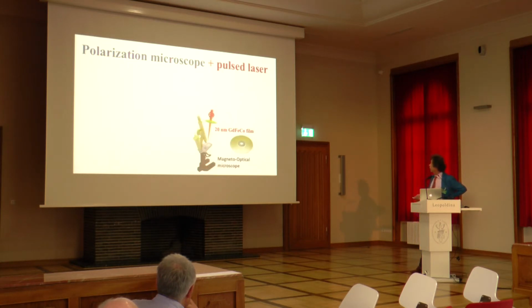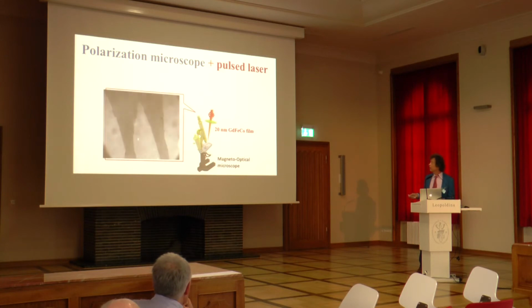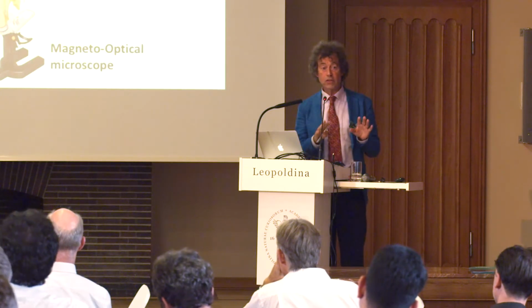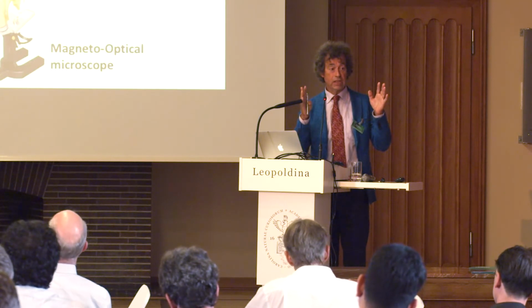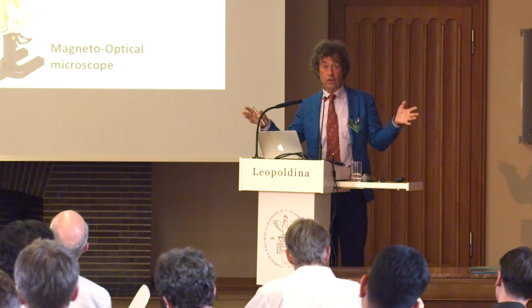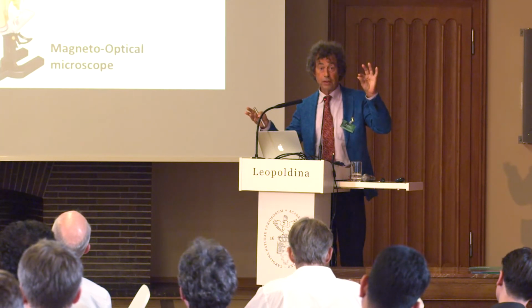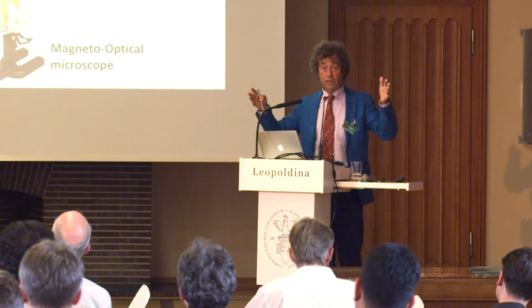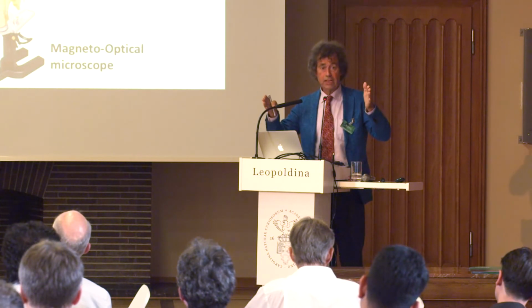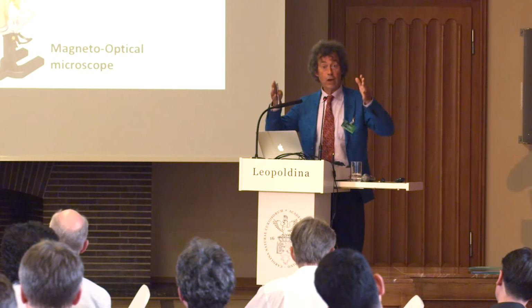So we took a magnetic disk with this magnetic alloy. It's only 20 nanometers thin, and there's no magnetic field here, so we just put it under a microscope. And then we can look at it. This is a polarization microscope, and you find this field of view. And what you see there are very large domains of magnetization up or down. There's no magnetic field applied. So that means if you have a very thin film, of 1 centimeter square but only 20 nanometers thick, it will break up in large domains.